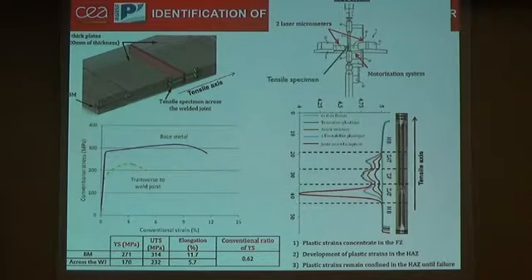So tensile tests were executed on a specific machine equipped with two high precision laser micrometers, which are in a periodic movement during tensile tests. And as a result, we can have the profilometry of the specimen during the tensile test. Here, for example, we have the profilometry. As we can observe, first of all, the plastic strain concentrates in the fusion zone, and then it is extended to the heat-affected zone, where it remains confined until fracture.